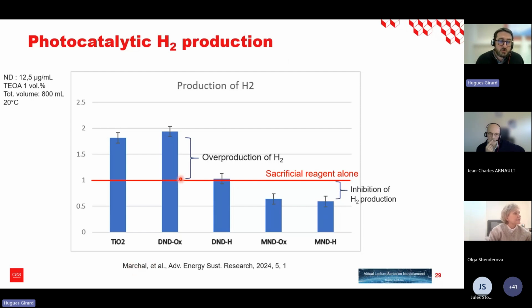What is important to see here is the comparison of the overproduction of hydrogen in presence of different types of photocatalysts. With titanium dioxide, which we used as a reference because this is a very standard photocatalyst that you can use for lots of different types of photocatalytic reaction, you can see that we have this overproduction of hydrogen. And the good point is that we observed a similar or even a little bit better overproduction of hydrogen in presence of oxidized detonation nanodiamond.